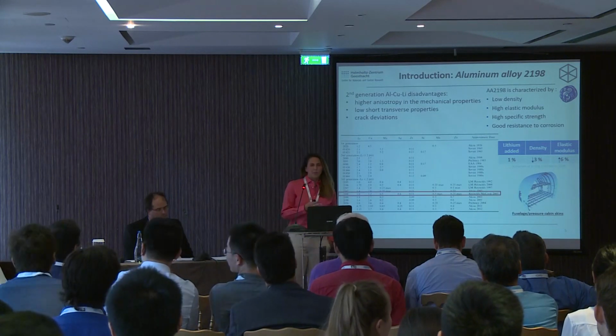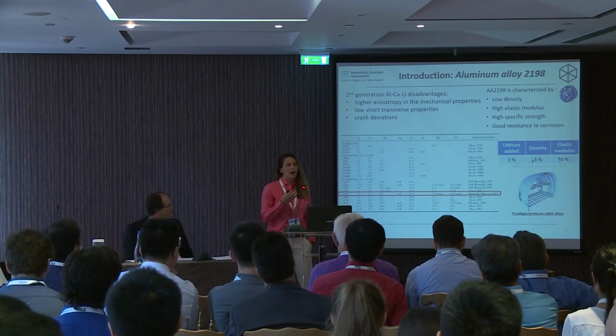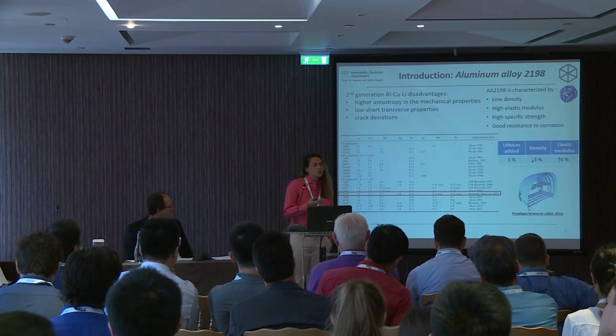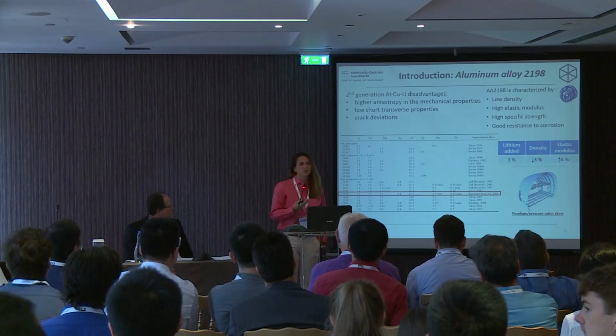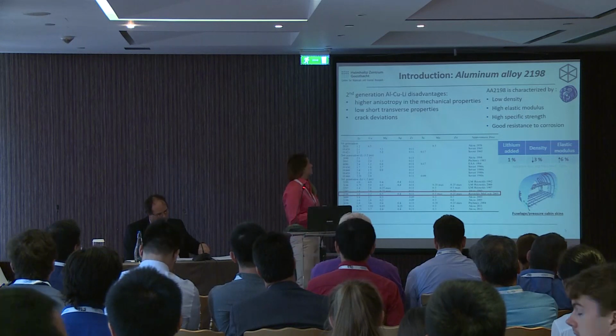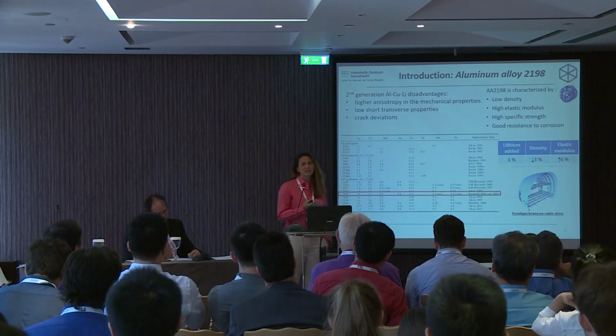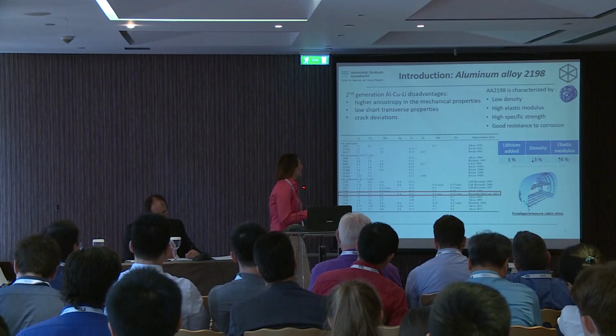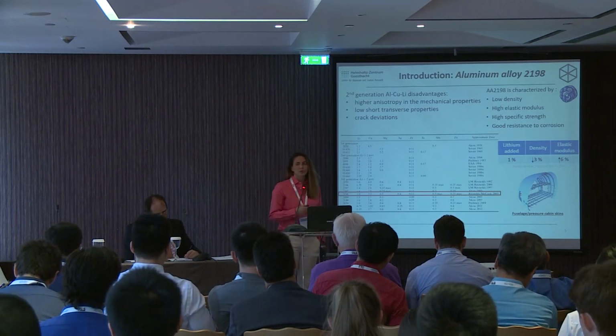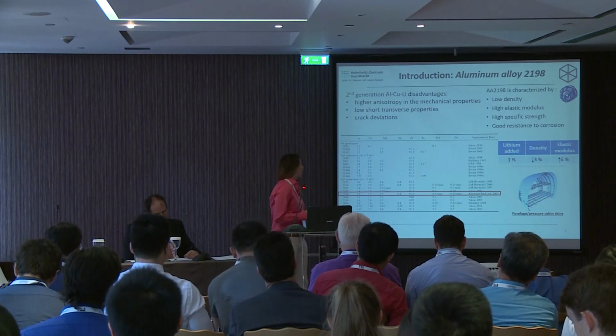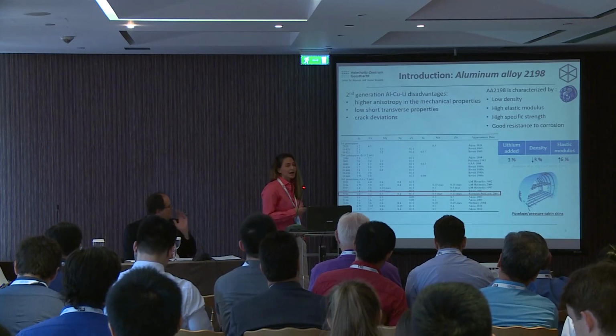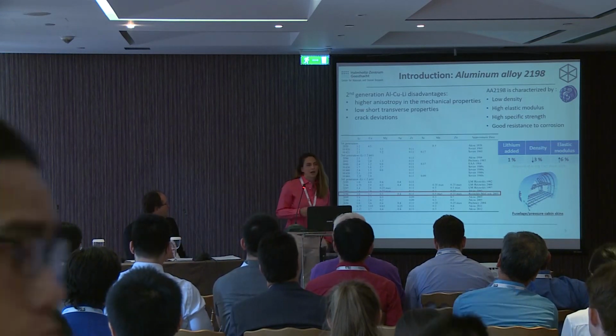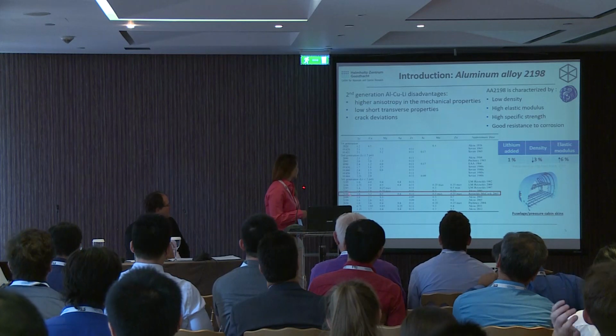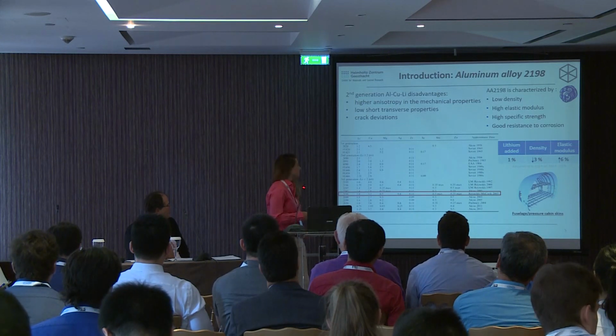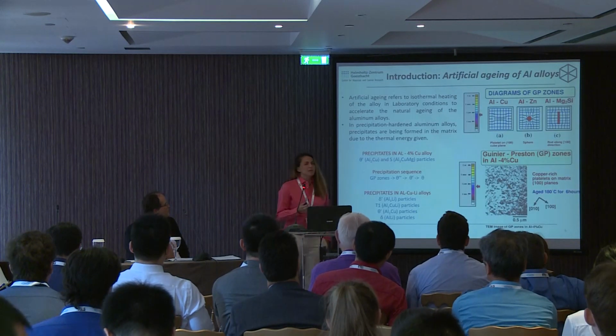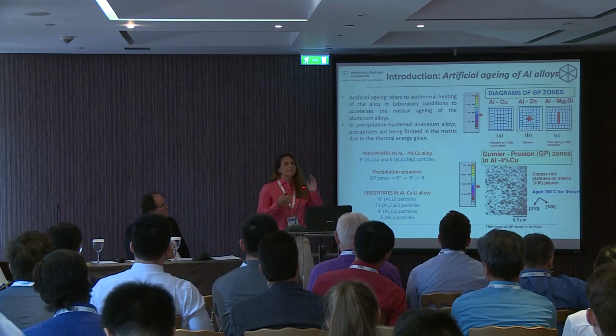Lithium is a metallic element with low density, and for that reason it was introduced to aluminum alloys to reduce weight. Nevertheless, this attempt had some disadvantages, such as higher anisotropy in the mechanical properties. 2198 is an aluminum lithium alloy, and it's in the third generation. This alloy is a precipitate alloy.